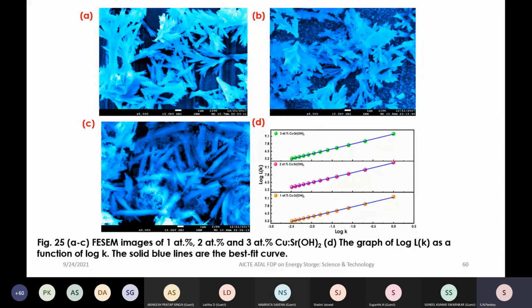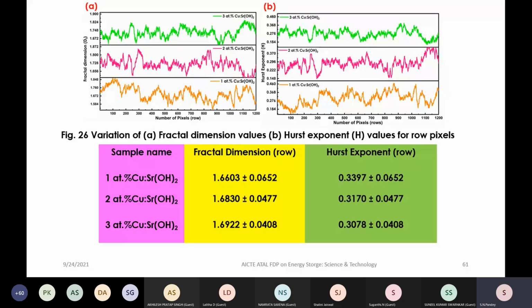This fractal nature can be seen for the 1 atomic percent, 2 atomic percent and 3 atomic percent doped copper strontium hydroxide. For these, the number of pixels and the fractal dimension have been calculated, and the number of pixels and the Hurst exponent have been calculated. Whether this corresponds to the obtained result or not, this is the theoretical one.